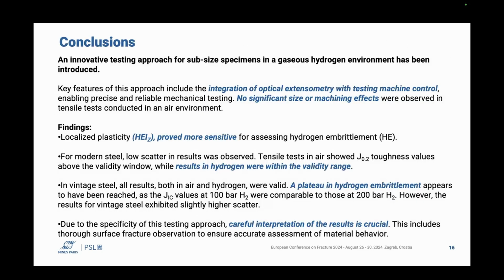So, to conclude, I presented here an innovative test setup to test mini specimens in a gaseous hydrogen environment. We found that by performing the integration of optical extensometry with the test machine control, no significant size or machining effects were observed in the tensile tests.